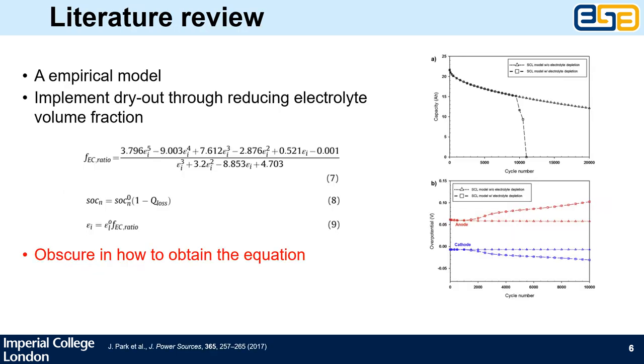We tried to dig into the literature and double-check whether there is some previous work on this. It turns out there is really not too much — we only found three. This is the first one. It has observed experimentally a sudden capacity drop. To capture this in a model, the authors multiply the electrolyte volume fraction by a step function here. However, it is unclear how to obtain this important function.